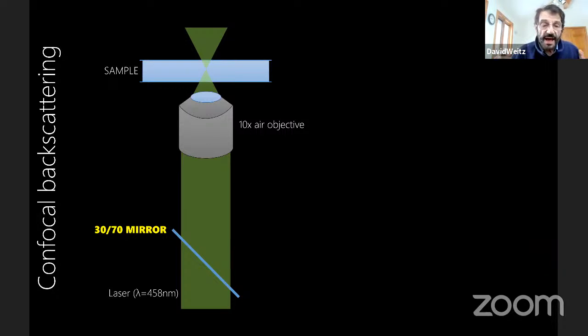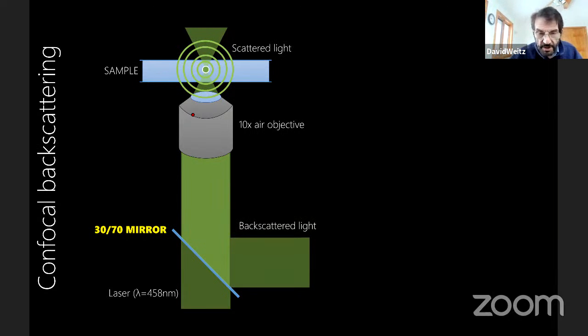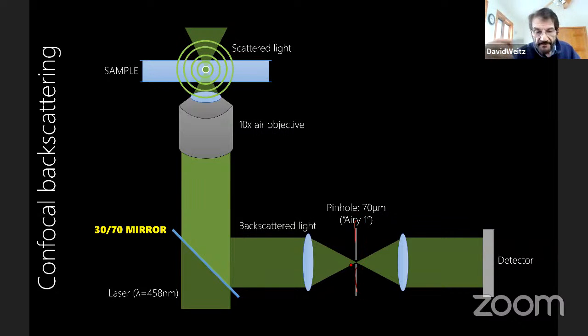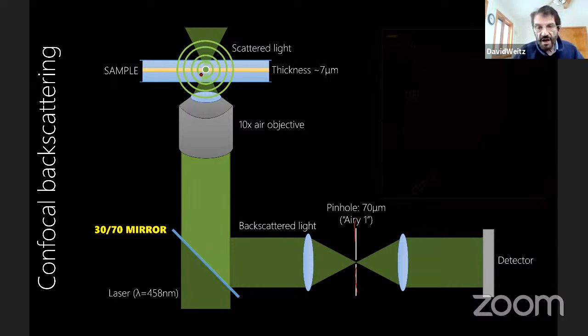He basically looked at imaging the sample, but he used a confocal microscope. So he just collects the scattered light. It's just the scattering from a confocal light microscope. He passes it through a confocal filter here, or a pinhole. And the point about the pinhole is that since this scattered light is from a laser, there are speckles, and by making the pinhole small, he can make the size of the speckles larger, but you still image. You're still observing the whole image. So each speckle actually corresponds to the scattered light from some region, and you get an image of speckles. And that's the important thing about the way you look at it.